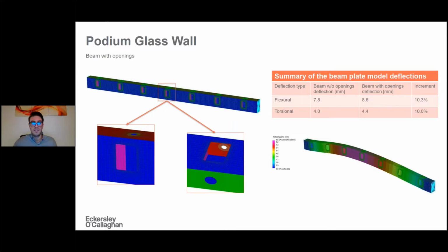And we did these plate models with openings and without openings to check what the difference was for flexural and torsional behavior. What we noticed is that the opening section was having roughly a 10% increment in the flexion, and what we did was just feed this into the global model by reducing the stiffness of the beam model, that's the beam element in the global model.